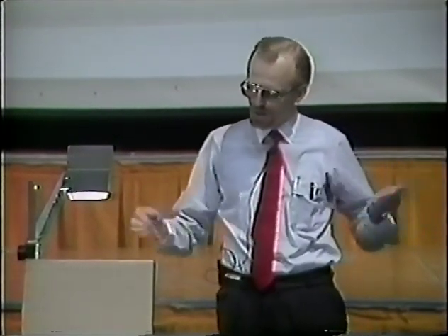The reason why palladium is slightly more complicated than nickel is that in the nickel case, the surface is permeable. So when you start to have release from the defect traps, the hydrogen goes to the surface, recombines, and goes into the vacuum, desorbs. However, in palladium, it turns out that when we have release from the traps, the surface is still impermeable.